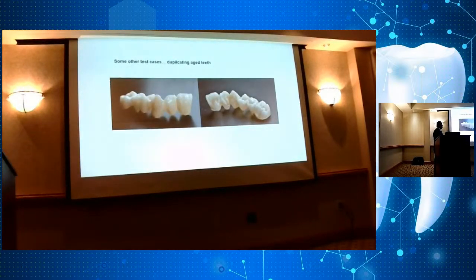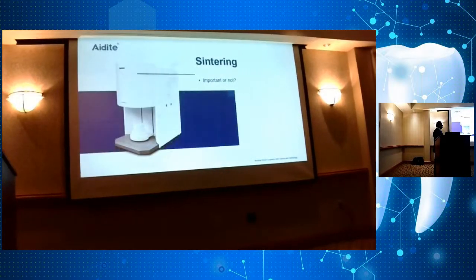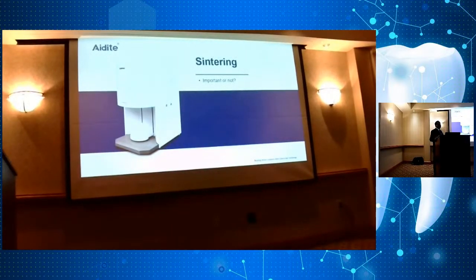This is the one that I did a long time ago, and I showed that to you. Sintering is extremely important, by the way. 90% of the issues that I have from people that don't get good results has to do with the sintering process. Everybody's oven fires differently. They have different elements and so on, lack of calibration, what have you. Almost 90% of the problems are related to sintering: bad coloration, yellow coloration, things falling apart in the oven, and mis-sintering.